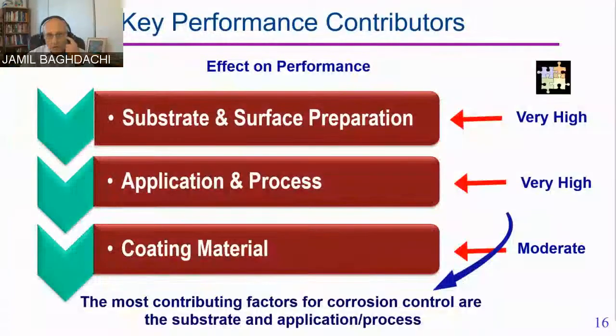I hope you don't get mad, because this is the reality of life, of course. I would say the key performance attributes of the typical aerospace coating are substrate and surface preparation. If we do that, then we have gotten almost 75% of the functionality of a coating. So, substrate cleanness and surface preparation. It is the one that many of the problems actually stem from. And again, myself and many, many people have already figured this out too.